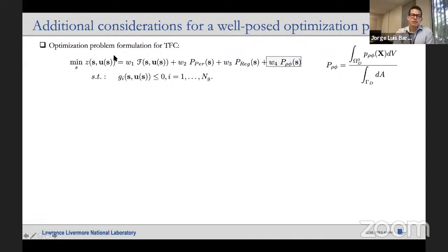Yeah, that's a good question. So a couple of things. First, all of these components are normalized, and the weights are chosen such that the contribution of what you really care about, the quantity of interest, is much larger than the other three. As long as this first one is between 85 to 95% of the entire objective, and as long as this one is larger than this or two, we're fine. So you have some leeway there. It doesn't have to be strictly 0.9, 0.8, or 0.95. Of course, your topologies change, but in terms of performance, it doesn't make a huge difference.